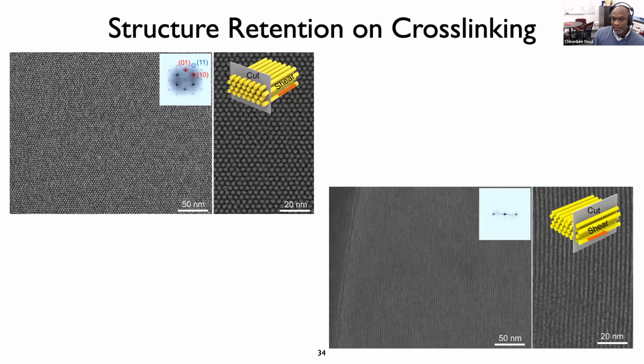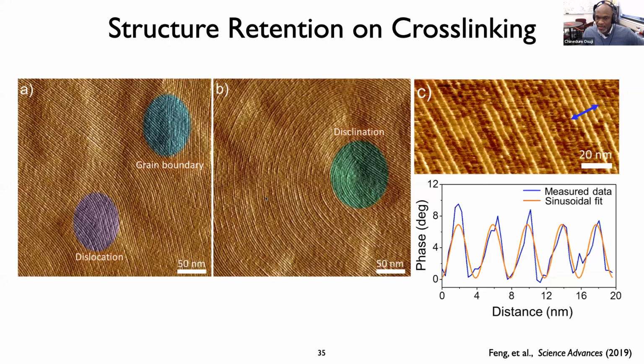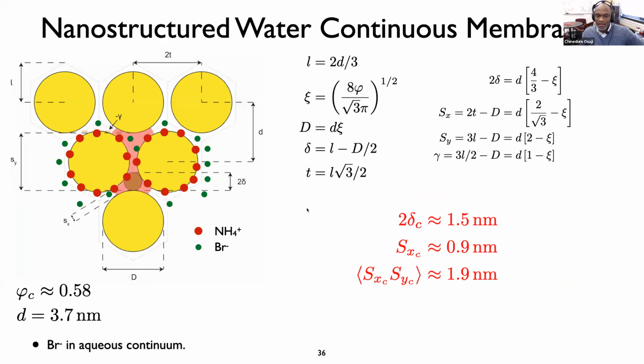We can see this by electron microscopy investigation. So this is TEM images looking down and perpendicular to the long axis of those cylinders. And the repeat distances here, the separations between the cylinders are on the order of a few nanometers. You can see this also by AFM imaging. And here you can see the topological defects that I alluded to that are responsible for some of the mechanical integrity of this membrane. The nice thing for us about these membranes and why we think this is potentially a nice addition to the portfolio of materials technologies that exist in the membrane space is that they truly are highly ordered regular structures about which we know a great deal, courtesy of the fact that they're regular and ordered.